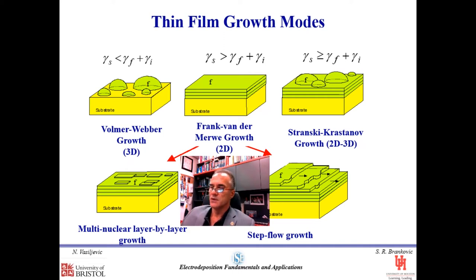So these inequalities between the surface energy of the substrate, film and interface define the growth mode, which we recognize as Volmer-Weber or 3D growth, then Frank-van der Merwe or 2D growth, and Stranski-Krastanov, which is the growth transition between 2D and 3D.